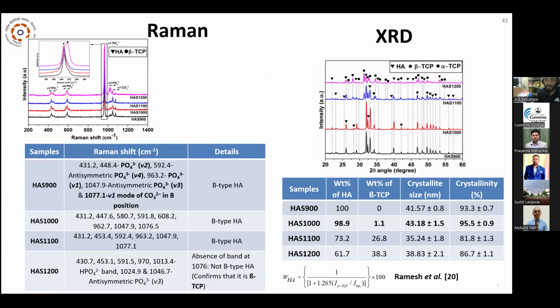Then coming to the characterization part, the first one is Raman spectroscopy, to obtain the Raman shift, basically to observe what type of powder is prepared. It is observed that at sintering temperatures of 900, 1000, and 1100, B type hydroxyapatite is prepared, and at 1200 some of the peaks are not observed, which basically confirms B type beta tricalcium phosphate. Basically, B type hydroxyapatite is suitable for bone tissue engineering.